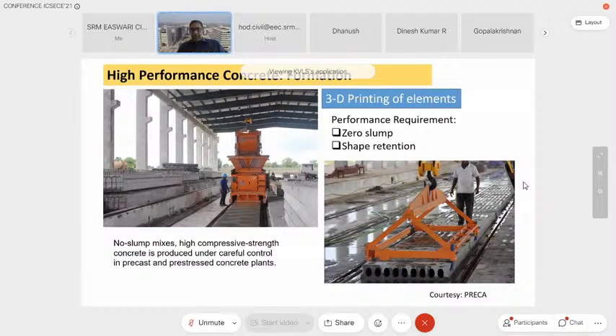If the concrete is not stiff enough, if it does not have the proper consistency, those holes will collapse, and I will not be able to produce the hollow core slabs. So this again requires engineering the concrete, engineering the fresh performance of the concrete to deliver this kind of performance. The concrete stays stiff, and I'm able to extrude it. That means it's able to flow under pressure, but as it comes out, it is stiff enough that it keeps its shape. So this is again another example of formation of concrete and performance requirement of concrete in the fresh state. And of course, if I stretch it now, the next step is 3D printing.